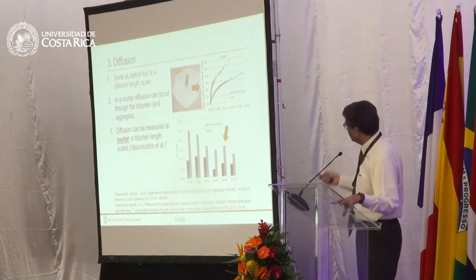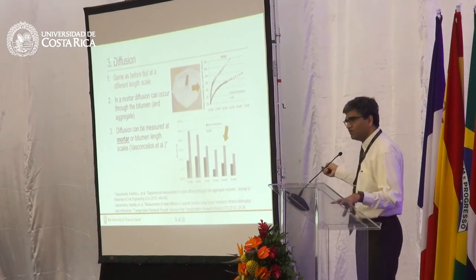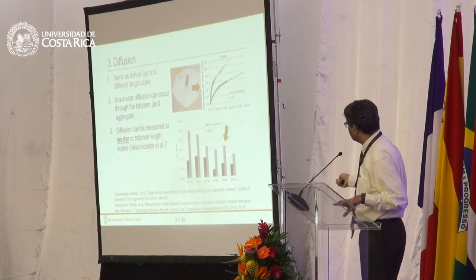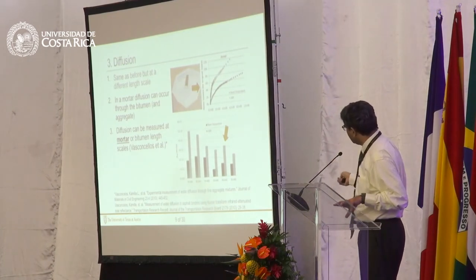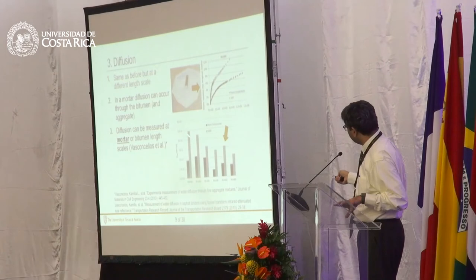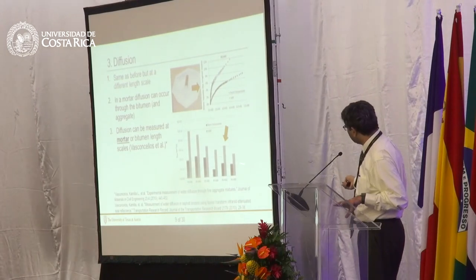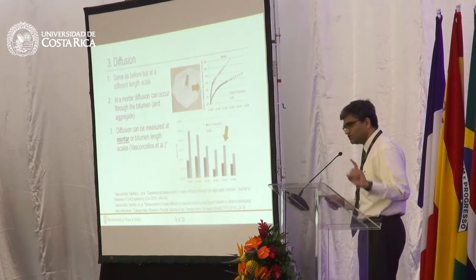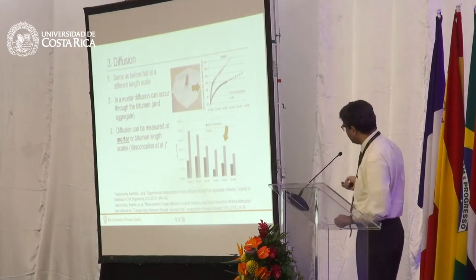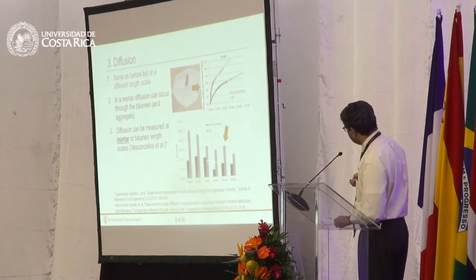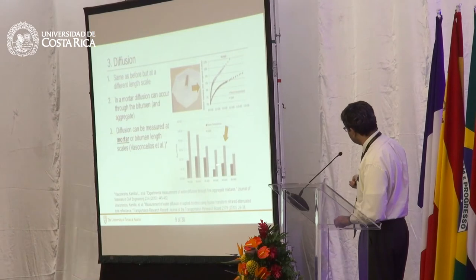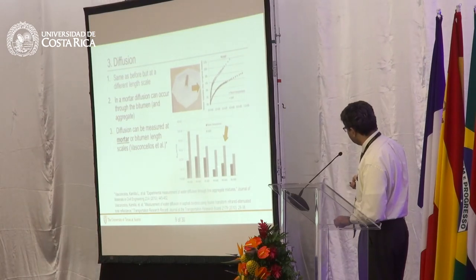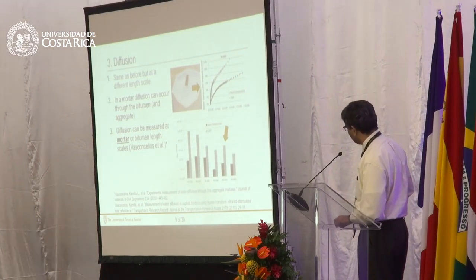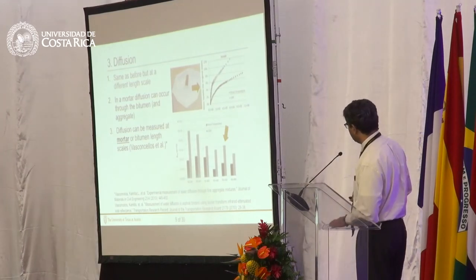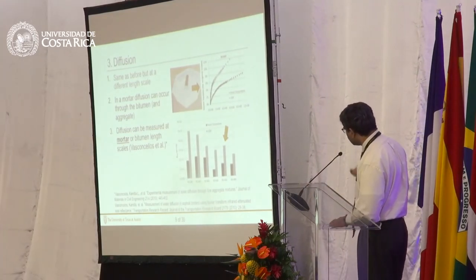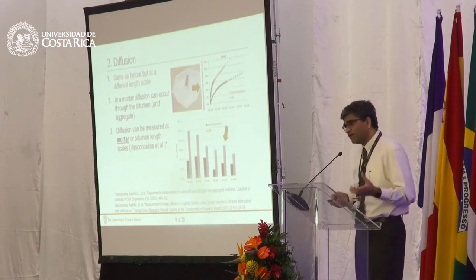You can actually open the book, look for this boundary condition, look for this geometry, and you can solve for the diffusivity constant. What you see here is a bar graph that shows that diffusivity constant for a number of different mortar combinations, combinations of asphalt binder and mineral aggregate, under two different temperatures. In this particular example, you can see these two bar graphs at room temperature and at 100 degrees Fahrenheit, which is approximately 39 degrees Celsius. So this is another property that can be measured.